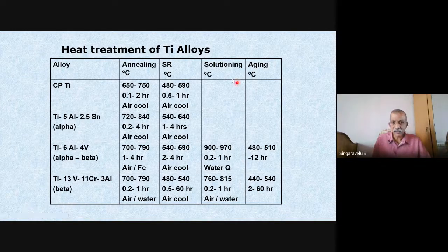Only for stress relieving, look at these temperatures, right? It is only 480 for pure titanium. In the alpha beta alloys, it is only 590. Alpha goes to 640 max. Within this range only, we will have to heat it and do the stress relieving operation.